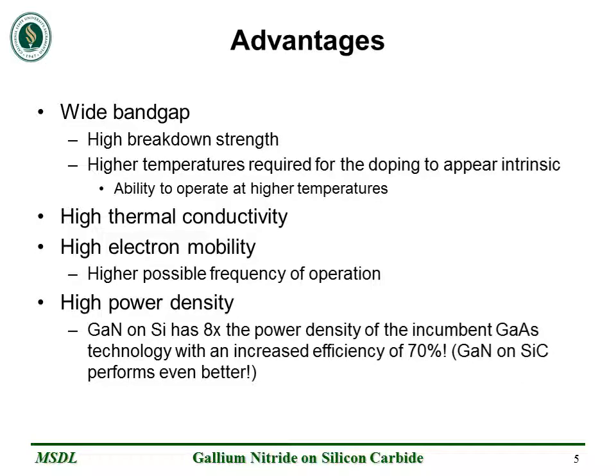A major advantage that gallium nitride and silicon carbide share is a wide bandgap. This means high breakdown strength and higher temperatures required for the substrate doping to appear intrinsic. As a result, much higher operating temperatures can be achieved. Silicon carbide has an especially high thermal conductivity, which is a great asset in high-power electronics. The high electron mobility of these materials means higher possible frequencies of operation.